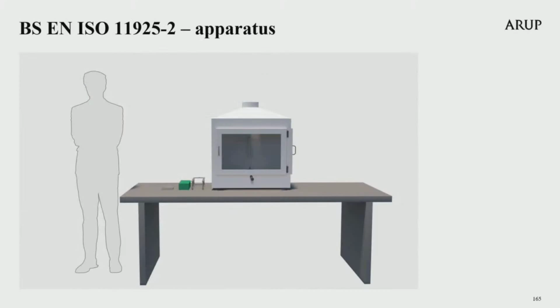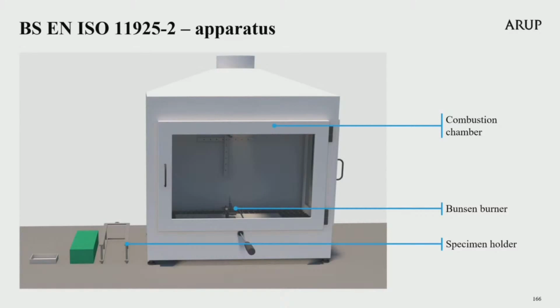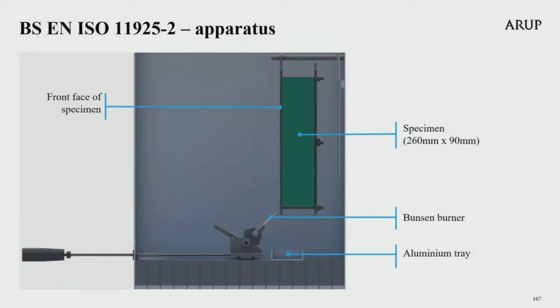On screen now is the apparatus for the single flame source test. The apparatus comprises a Bunsen burner housed within an outer housing called the combustion chamber. The image on screen now shows a cross-section through the combustion chamber, looking side on. The sample is suspended from the back wall of the outer housing, and the Bunsen burner is mounted onto a horizontal plate so that it moves smoothly forwards and backwards in a horizontal plane along the centre line of the combustion chamber. An aluminium tray containing sheets of paper is placed below the sample so that any flaming droplets will land on the paper and potentially ignite the paper.